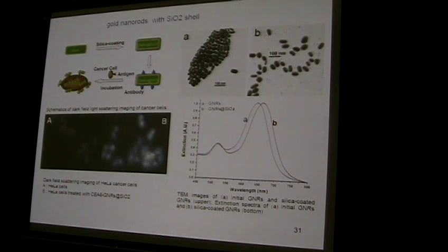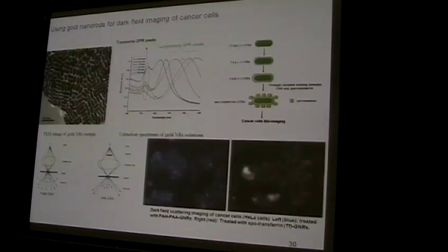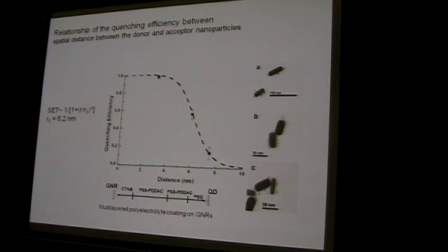Oh yes. Particularly for the quenching effect, we have this kind of curve. If you want the quenching efficiency to be high, to see the quenching clearly, you need to be very close. You see here at this level, like 4 nanometers, 5 nanometers, you need to precisely control them. So we're using these polymer coatings or silicon oxide. By controlling the reaction time, we grow them. So it's very close to the surface.